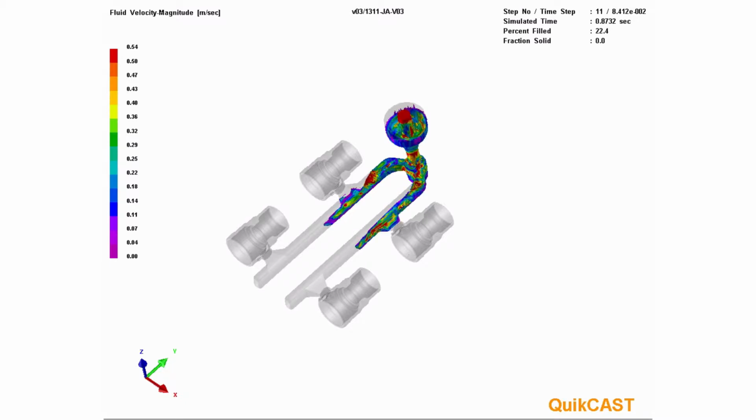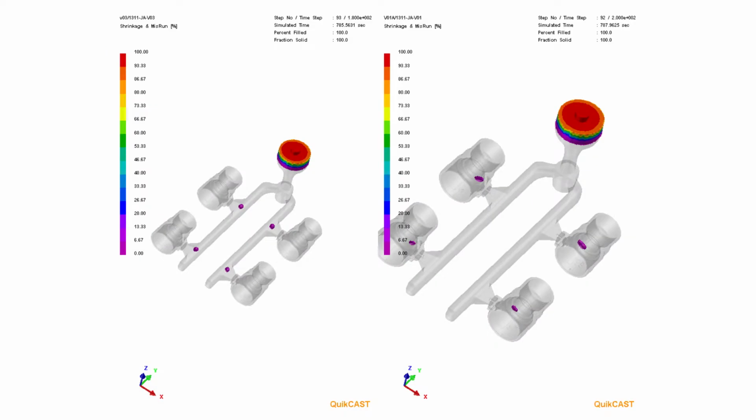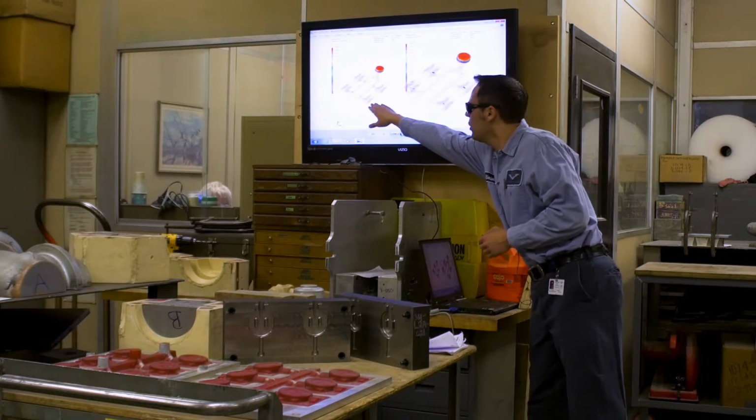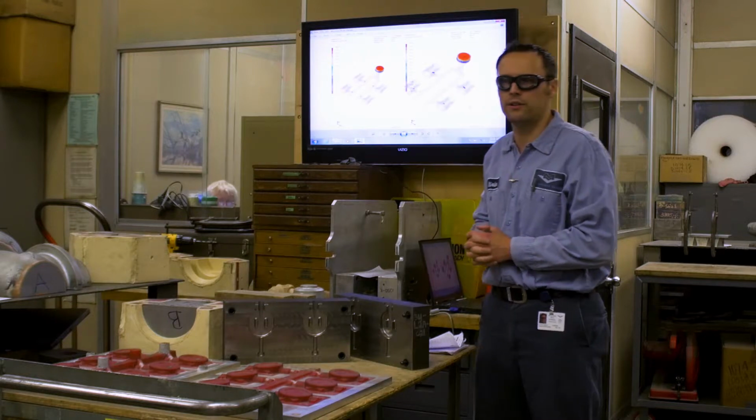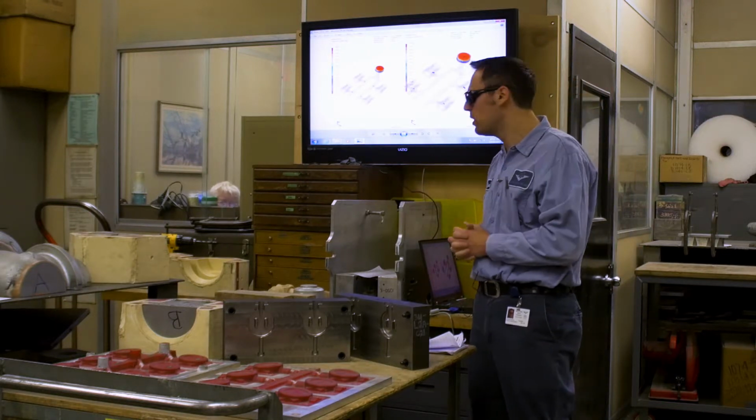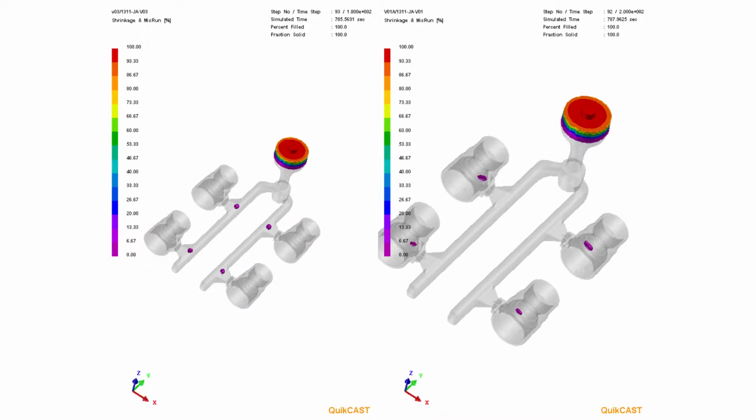What we do is look at common defects in casting, for example shrinkage porosity. Obviously we had a gating design on the right-hand side where you had shrinkage in your casting, so you don't want that. So we changed the gating and we're able to pull the shrinkage inside the gating, which is what we want, so that the gating gets recycled. That's not something we send on to the machine shop. So that enables us to run design iterations before even having to cut the tooling.